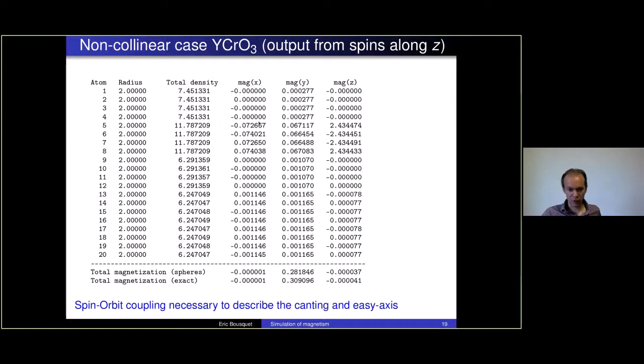But we can see here we have something that is slightly non-zero away from the Z direction. And if you check carefully, you see indeed along the Y direction, we have about 0.06, 0.06, 0.06. So all the magnetic moments have a small component along Y in the same direction. This means that along Y, if you make the sum, you have a non-zero magnetization. And if you look along the X direction, you also have a small deviation that is non-zero. But you see here you have minus, minus and plus, plus. This means that the small deviation along the X direction makes a sum that is 0.